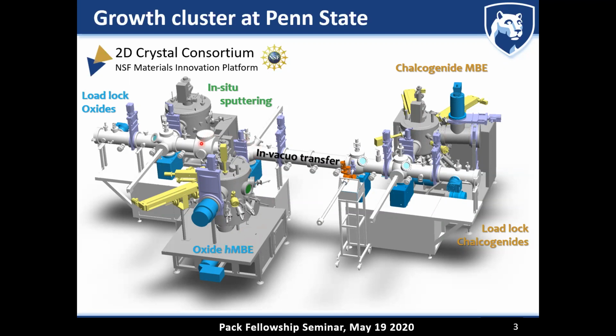But then we can also grow oxides. In fact, it turns out that the way we started this growth cluster, we first had the oxide system, and then we attached the chalcogenide system. And one of the unique capabilities is that we have an in-vacuum transfer. So we can start growing oxide films and then transfer them in vacuum to the chalcogenide system.